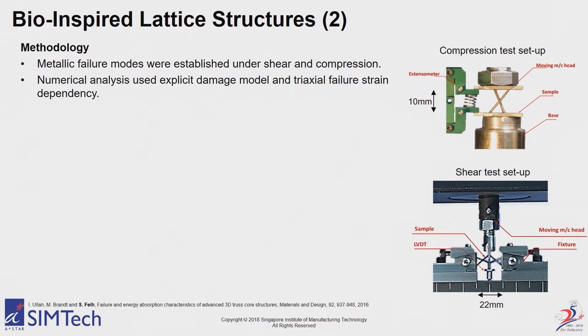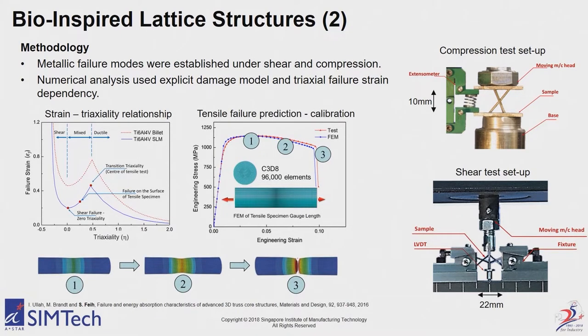So the first thing we did was to say, okay, let's actually look at standard tensile specimen. We can do this in Abaqus Explicit. We can put in a ductile failure model. We used a failure model with triaxiality, so where the failure strain depends on the stress state. That is very important. If we're looking at tension and compression and shear, the failure strain will be different. The input curve is the same, but the strain values where damage and basically failure happens is different. And for the bulk material, we could actually predict this very well, and we calibrated the model.